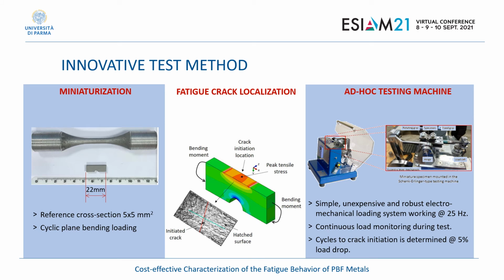To apply this cyclic bending moment, we developed a testing machine specific for this small specimen, working at 25 Hertz, and it's an electromechanical system that continuously monitors the load during the test and can easily perform fatigue tests in the long range.